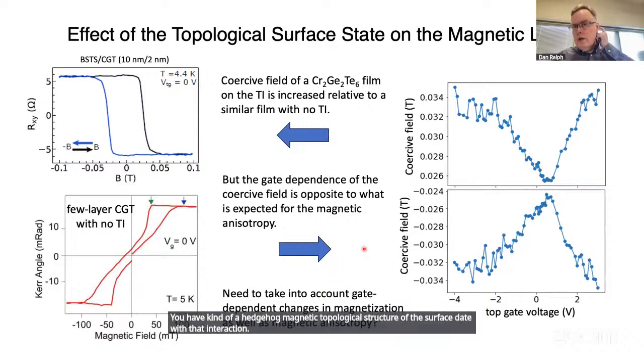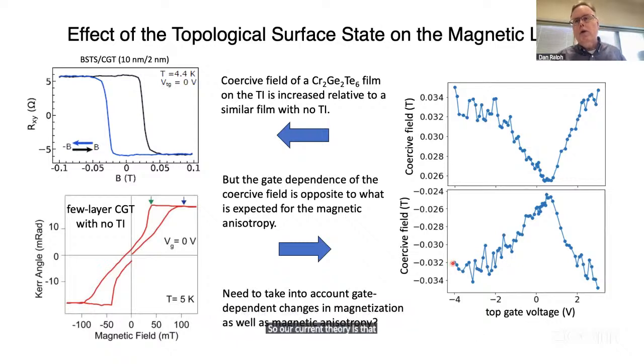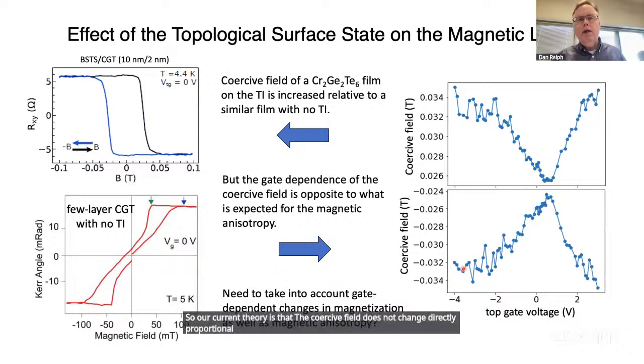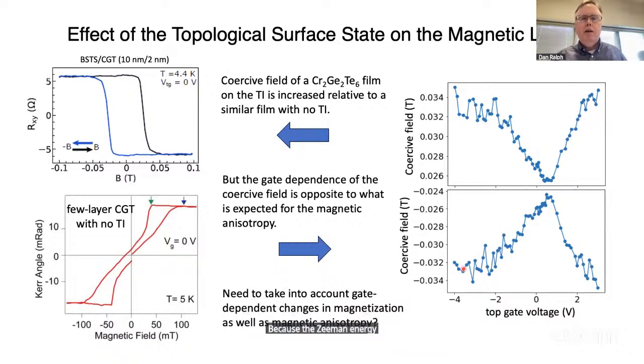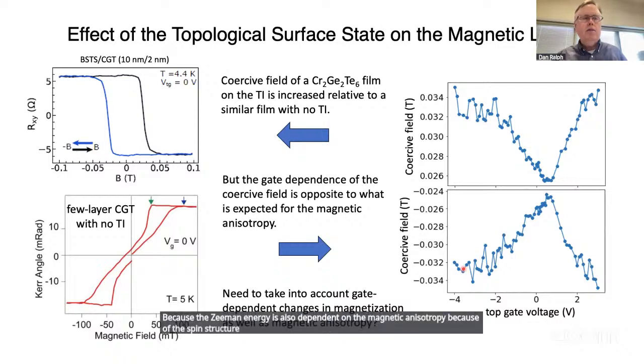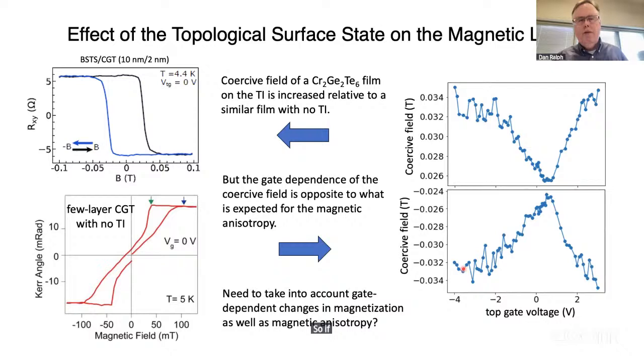So our current theory is that the coercive field does not change directly proportional to the anisotropy because the Zeeman energy is also dependent on the magnetic anisotropy because of the spin structure within the topological surface state. So if there's people interested in thinking more about that, we're still kind of puzzled about this, but yeah, this is something we are finding very interesting.